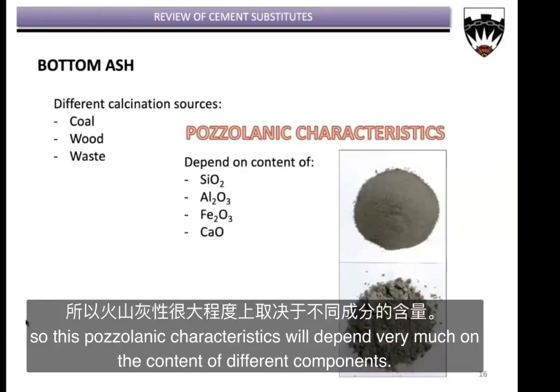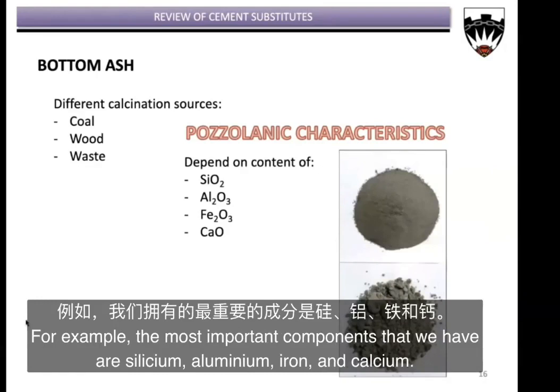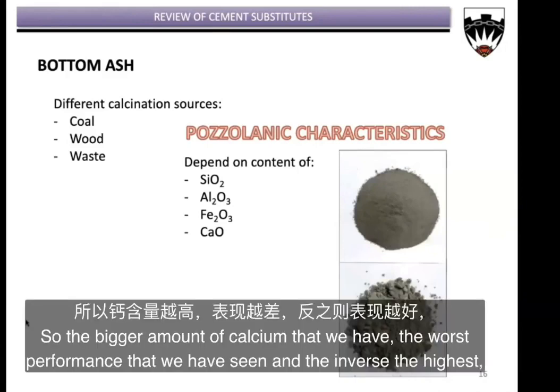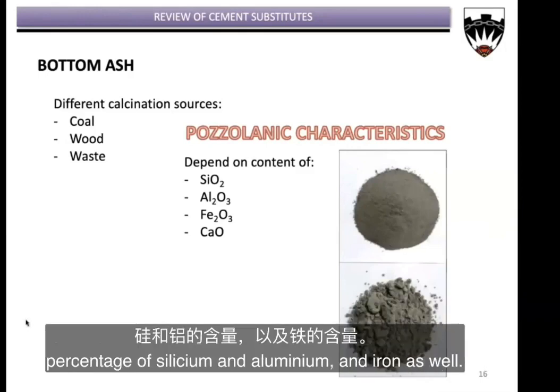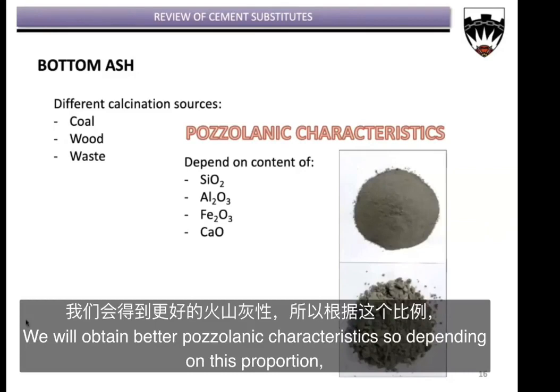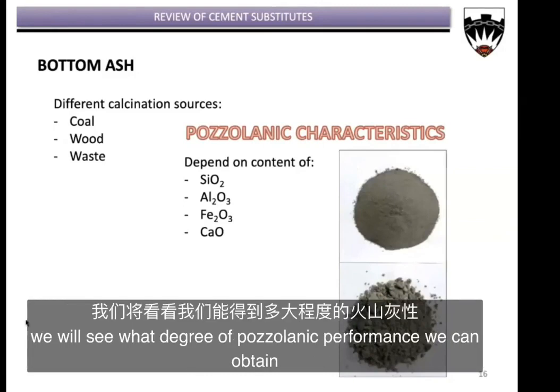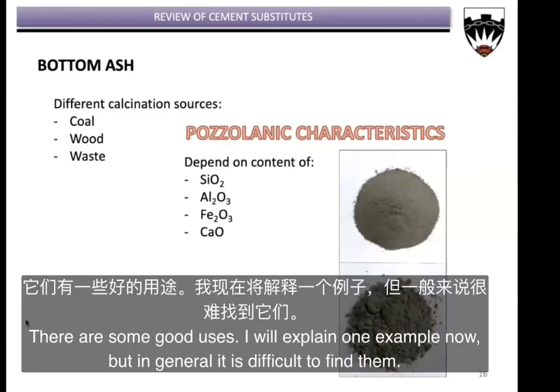So these pozzolanic characteristics will depend very much on the content of different components. For example, the most important components that we have are silicium, aluminum, iron, and calcium. So the bigger amount of calcium that we have, the worse performance that we obtain. And the inverse, the higher the percentage of silicium and aluminum and iron as well, we will obtain better pozzolanic characteristics, right? So depending on this proportion, we will see what degree of pozzolanic performance we can obtain, right? There are some good uses. I will explain one example now, okay? But in general, it is difficult to find them.